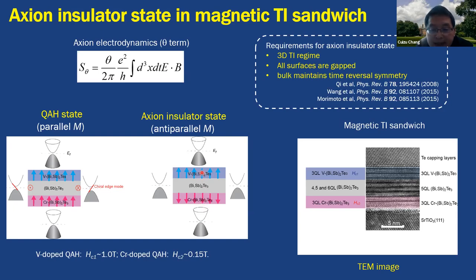And the Hall conductance from the top surface and bottom surface will cancel each other, and the total Hall conductance will be zero. This is the transport point of view to understand the axion insulator. When they are in parallel alignment, this is just a quantum anomalous Hall state, because each surface contributes e squared over 2h, so the two surfaces contribute e squared over h. So this is the quantum anomalous Hall state.